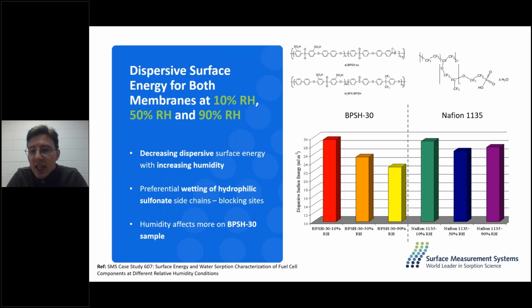Conversely, we can see that the Nafion membrane is now having a much different interaction than we were seeing before. So we can see that it somewhat stabilizes its dispersive surface energy when we get to 50 and 90% relative humidity. So if you were screening the two membranes as to how they would look in a water fuel cell membrane, you can see that Nafion not only has the higher dispersive surface energy, but is less likely to change that energy as a function of humidity.